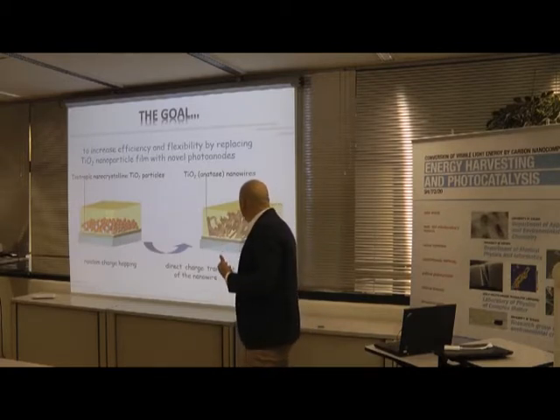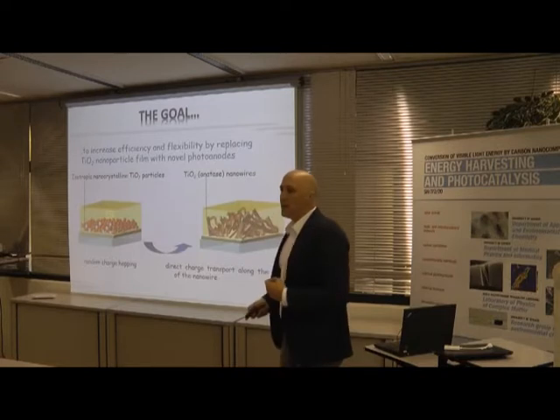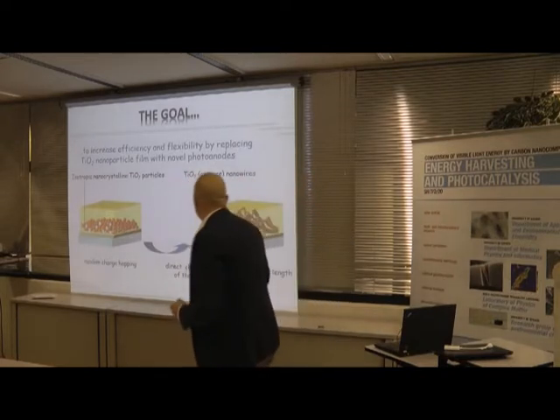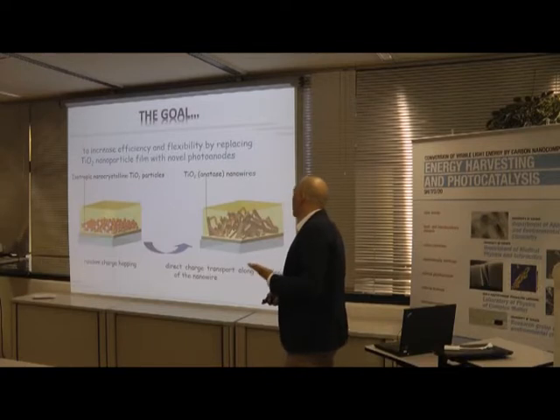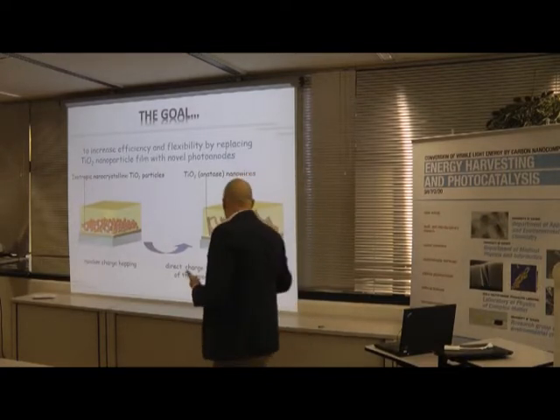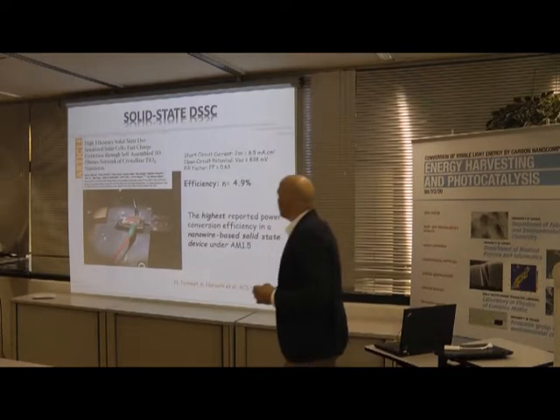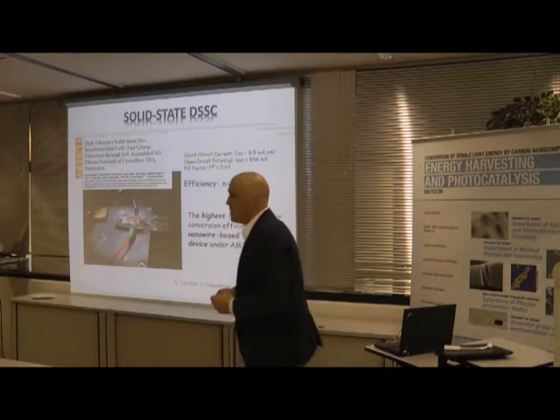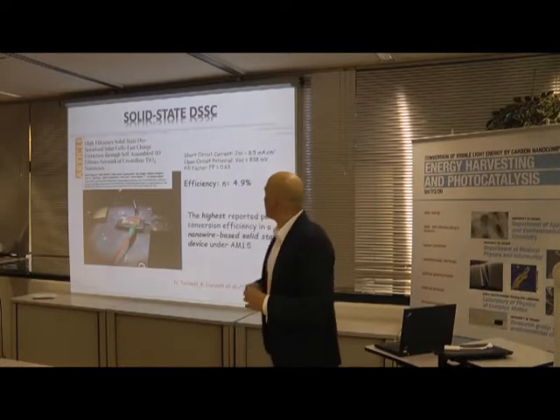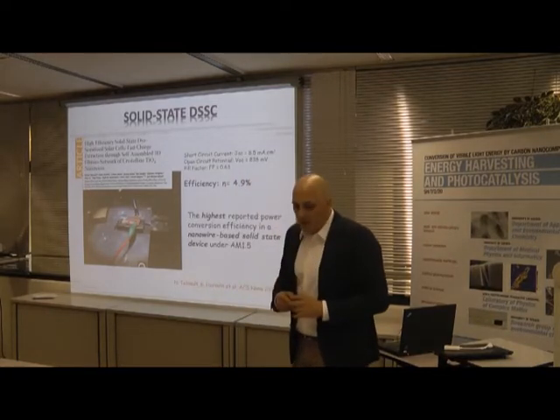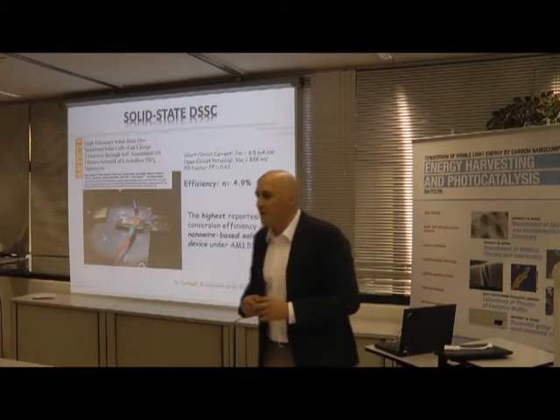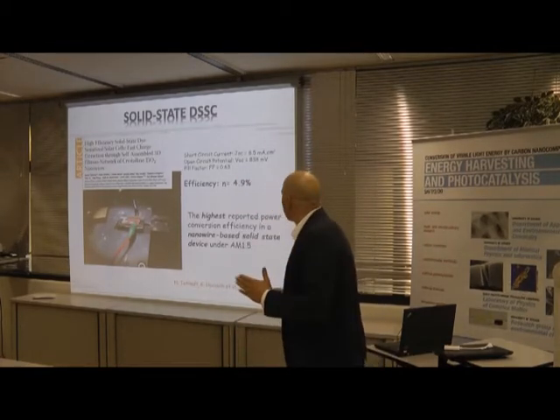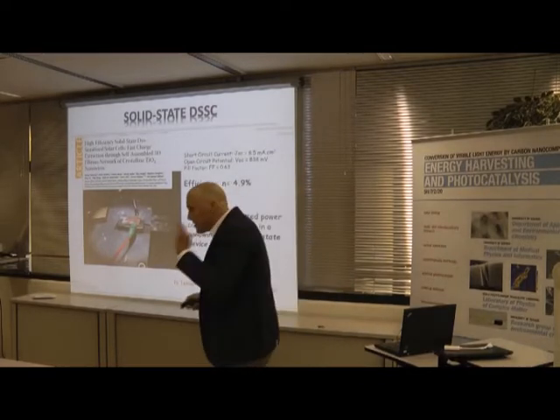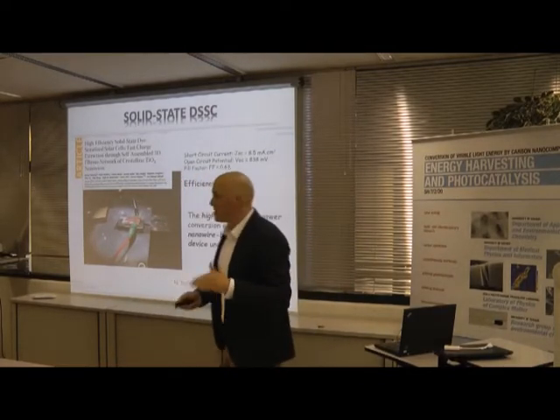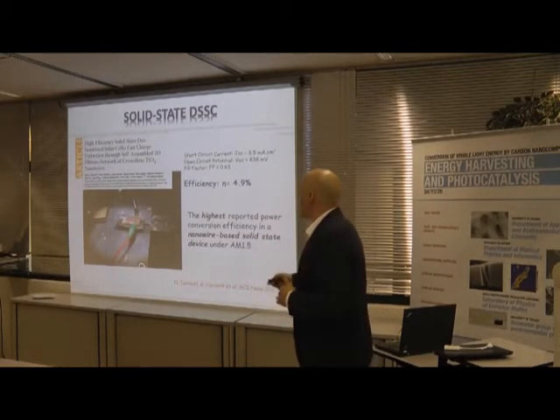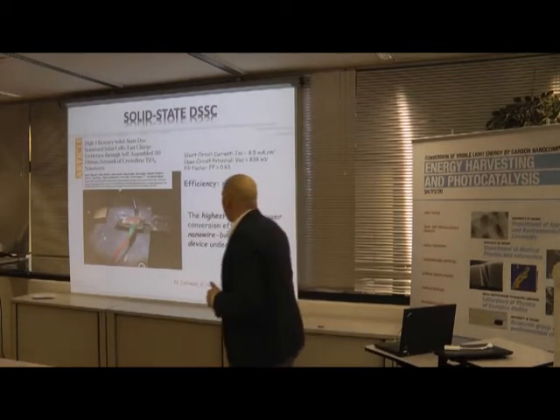the light-induced charges. They travel until the electrodes, and you can probably use them with reduced losses as compared to the other system. So in around 2010, we implemented the nanowires in so-called solid-state dye-sensitized solar cell, where we reached efficiencies of 4.9%. At that time, it was just below the record. The record was 5.1%. So because of the 0.2%, we couldn't publish it in a higher impact journal than ACS Nano, but we were quite happy with that.